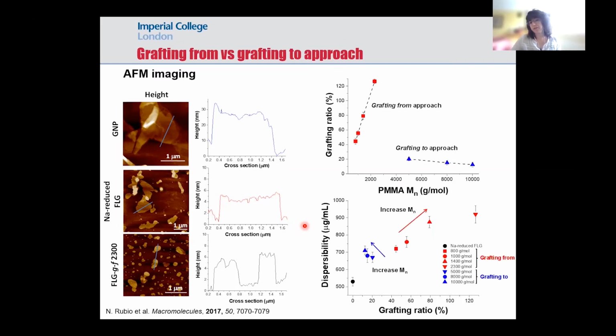This graph is a good summary of both approaches and how they compare to each other. We can observe the grafting ratio versus the polymer molecular weight. For the grafting-from approach, as we grow the polymer on the surface, we observe an increase in the grafting ratio as we increase the polymer molecular weight. And on the other hand, in the grafting-to approach, we observe the opposite trend. We observe a decrease in the grafting ratio as we increase the molecular weight, probably due to a higher steric hindrance of larger polymer molecular weights.